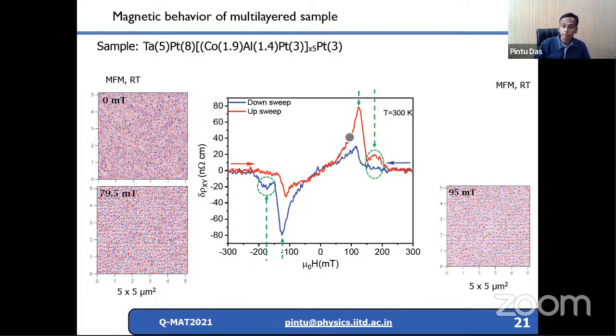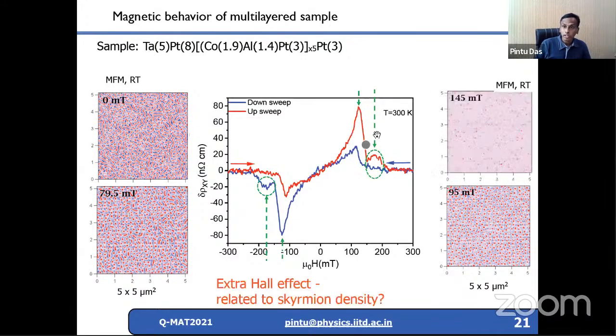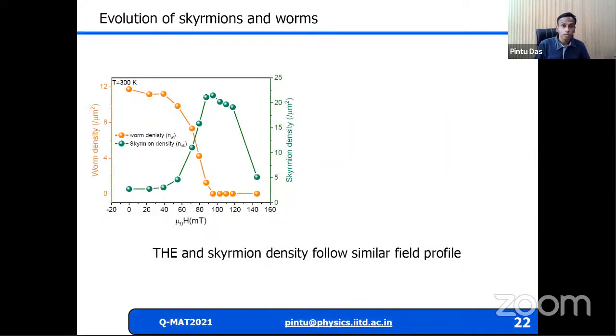And then at about 95 millitesla, the density increases further, so the signal is increasing further. And lastly, when it is going to saturation, the number density is decreasing, so here the signal is decreasing. So this extra Hall effect is related to skyrmion density. What we have done is calculate the skyrmion density and worm density as a function of field, and we see that there is a peak appearing in the skyrmion density at around 100 millitesla.